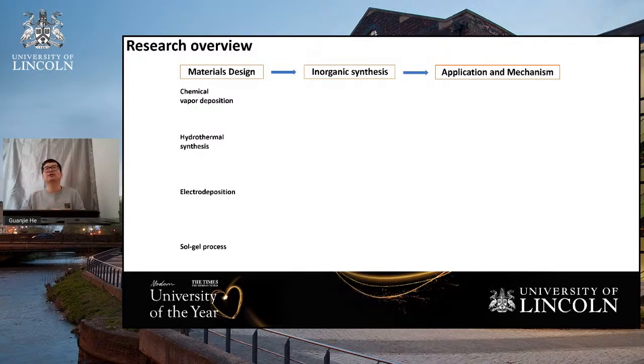As for the commercial or traditional electrode making process, we have these active materials, but those are in powder. We need to make a slurry with a binder and paste them on the current collectors. This process is relatively time consuming, and we also need extra equipment to do that. My strategy is to form strong bonding with current collectors and form the composite materials directly with the current collector.